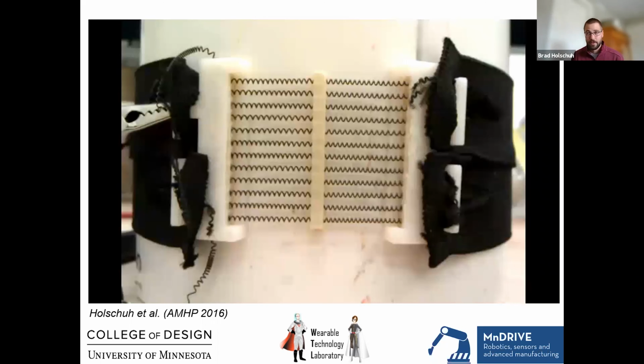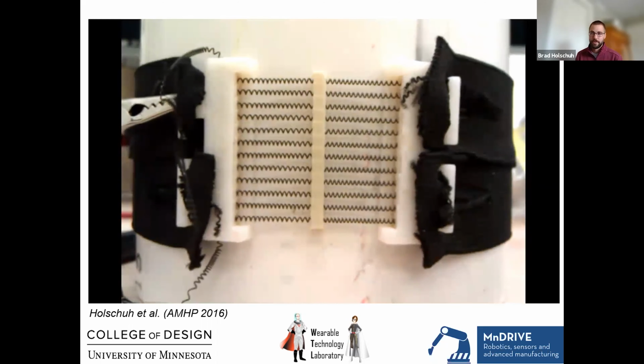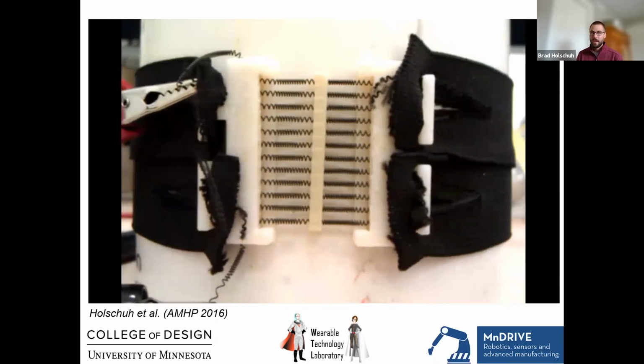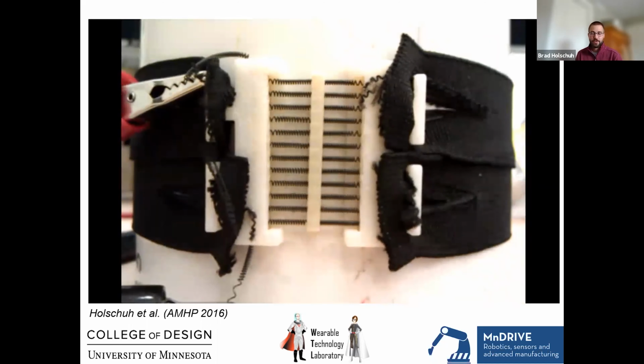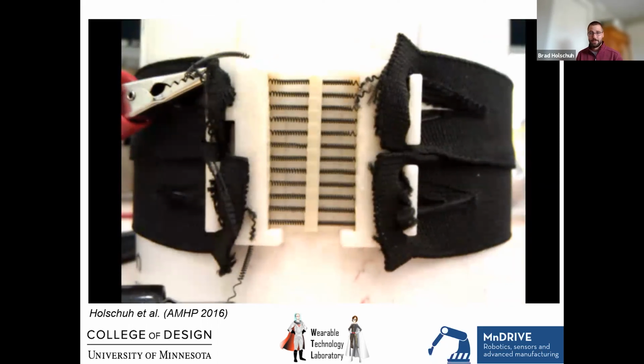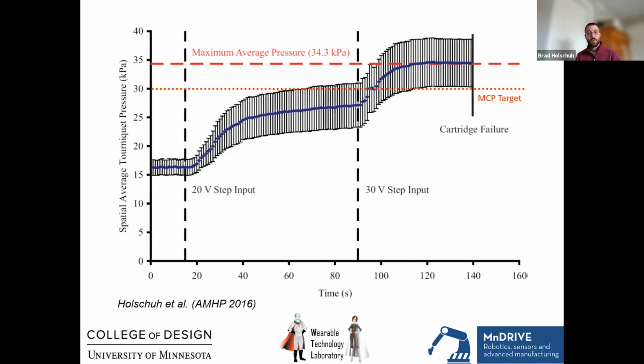So you're all probably asking, what does this look like in action? Well, here is what a set of these actuators can do. So this is a video. There's, I think, 12 of them run in parallel with each other, hooked up to a power supply. And you apply a current through those actuators, and you see a contraction. Right? That's a linear artificial muscle. And in this case, it wasn't a very large centimeter scale contraction, but doing that paired with a really, really stiff fabric can produce monumentally high pressures without requiring very large displacements. And on this chart, you can see precisely what that looks like.